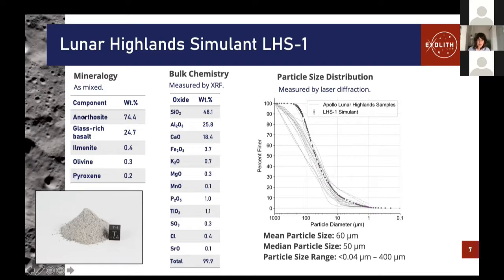It's mostly anorthosite, which is mostly the mineral plagioclase. We also add in a glass-rich basalt, and that serves two functions. There's some basalt present in the lunar Highlands that has been transported from the Mare region. But the fact that the basalt is glass-rich allows this simulant to simulate some of the properties of the glassy component of the lunar regolith. We are working on an agglutinate simulant, and I will talk about that in this talk, to do that a little bit better. But for somebody who just wants to buy a huge amount of this for their rover test bed or something, this does a pretty good job. And then there are smaller amounts of the iron titanium oxide ilmenite, and olivine and pyroxene.